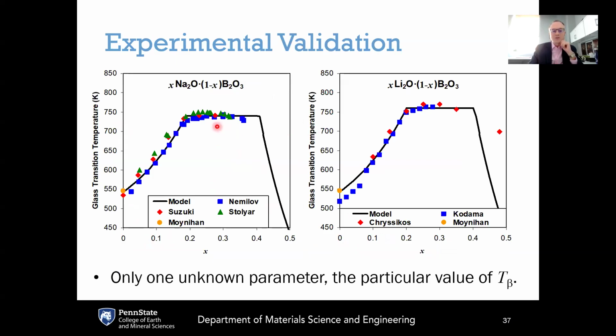And that can be deduced quite easily by just looking at the experimental data, where you can see that, in fact, there is a flat region here of the glass transition temperature as a function of composition. So this shows experimental data, the points, versus the model, which is the black curve, and that is an analytically derived model using temperature-dependent constraint theory. So this shows you the power of both temperature-dependent constraint theory and, in general, statistical mechanics to be able to predict the evolution of property values.